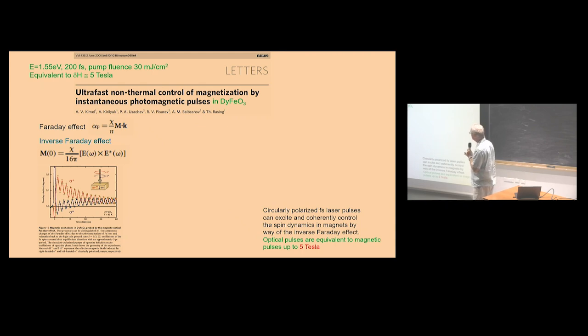Another important paper was published by this group in 2005, when they observed the inverse Faraday effect. In the Faraday effect, you see the rotation of the beam polarization proportional to magnetization. But in the inverse Faraday effect, they practically induce a magnetic field or magnetization using a circularly polarized beam. You can imagine that you have circularly polarized light, left-handed or right-handed, and you can induce magnetization, and this magnetization depends on the handedness of the circularly polarized beam.